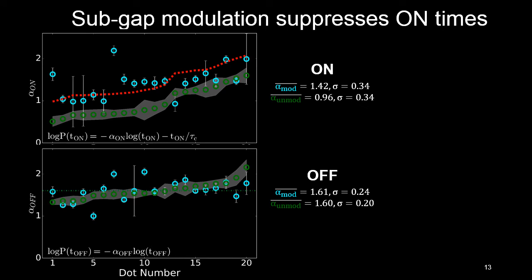By contrast, looking at the on slopes, we see a clear increasing trend. This data is for the exact same dots as you see below, and again the green circles are plotted in increasing order, but now the corresponding modulated or blue data appears to lie above the unmodulated data in almost every case. Looking to the right, we see a very clear change in the average slope.